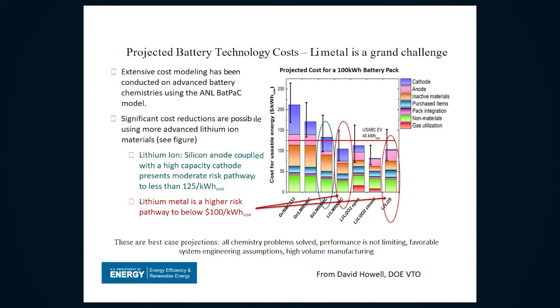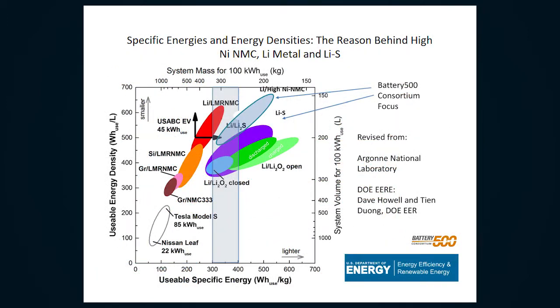So this is why we think that, good news for you, you have a big job to do. We think lithium metal is really a very important thing for the next generation batteries. And then there are two systems we can look at. One is to use the mixed oxide cathode material, increase the voltage, increase the capacity, particularly go to high nickel NMC, couple that with the lithium metal, that can get you to the lowest cost, and also the highest specific energy at this time. So this is the lithium metal coupled with high nickel NMC system.